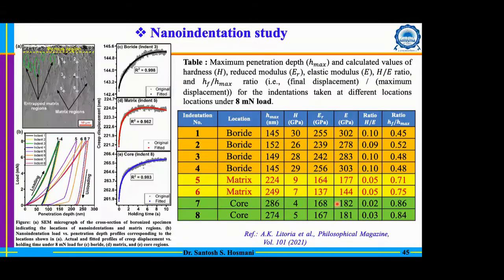For that purpose, we did a nanoindentation study. What we observed is that borides are definitely harder, though that is not well reflected in the table here. And the modulus of the boride is high, which is obviously expected, compared to the matrix, meaning the region surrounding the boride, and the core region, the non-boronized core. Here we see that the E value, the modulus of elasticity, is definitely high for the boride.